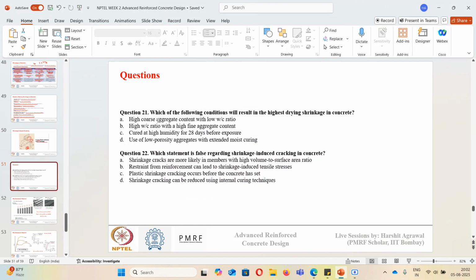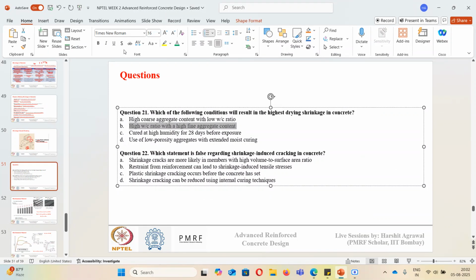Okay, so yes, for 21, the correct answer is B. Which of the following conditions will result in highest drying shrinkage? Higher W by C ratio or higher fine aggregate content. So this increases the cement paste volume inside the concrete, and the more the moisture and the more the paste content inside the concrete, there will be more chances of moisture evaporation, and thus more chances of shrinkage. And higher W by C ratio also reduces the strength of concrete, so that can also increase the chances of cracking due to shrinkage.